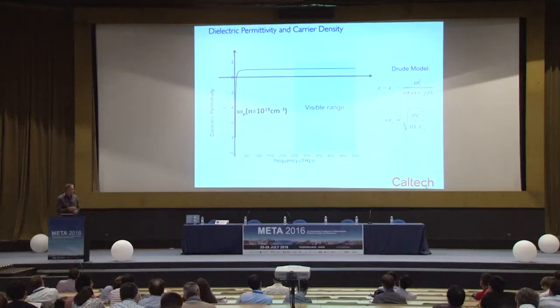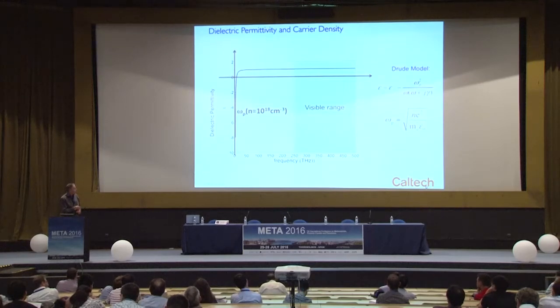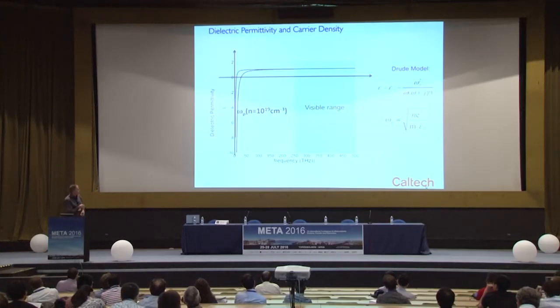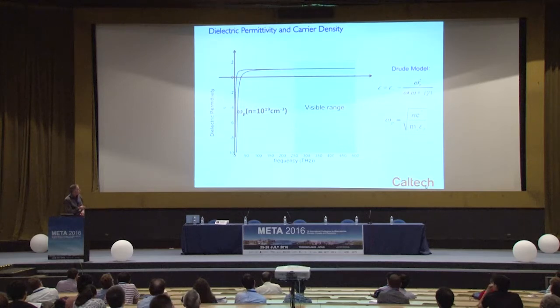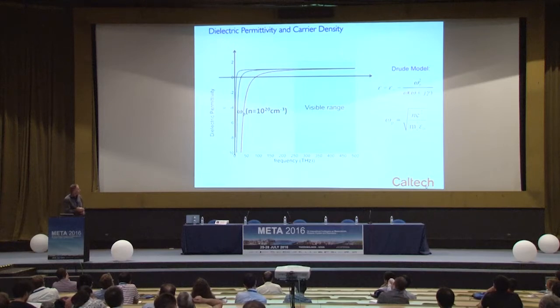And that accords with our everyday experience with the complex index of lightly doped semiconductors. But of course, even in the far infrared, such materials have sufficient conductivity to exhibit negative permittivity and be plasmonic. So we can see that in this regime, as we modulate the carrier density, there's very little change in the permittivity. For example, if I change the carrier density to 10 to the 19, either by doping or field effect modulation to change the local carrier density, you can see that in the mid to far infrared we see a significant change, but in the near infrared and optical range we still see hardly any effect. So to really have a strong effect, we need to go to higher carrier densities characteristic of semi-metallic materials, things that lie intermediate between dielectric and metallic materials.